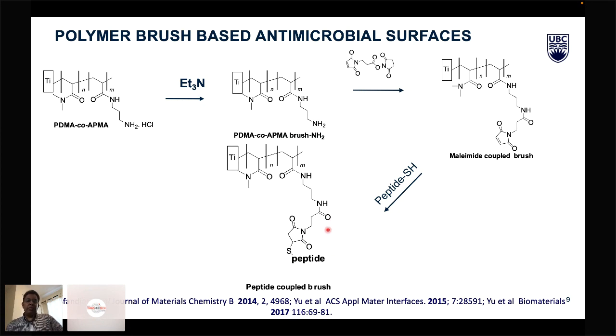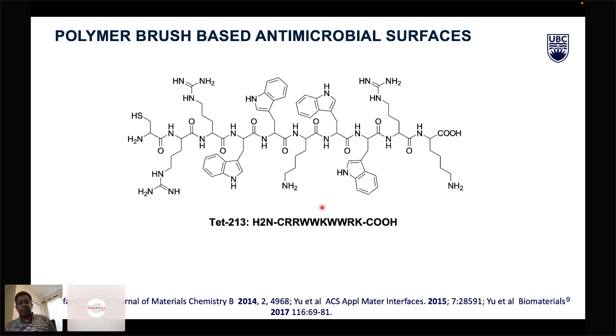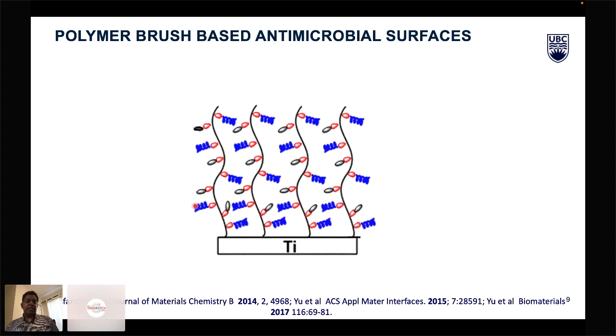And the most important aspect is that we could change the polymer, and we could change the length of the polymer, which determines how much peptide can be attached, and we could also change the peptides as needed. A diverse range of antimicrobial peptides are available, and this is one example of those. So you have a variety of peptides available, and you could utilize this concept to generate a surface coating which is anti-adhesive as well as antimicrobial.